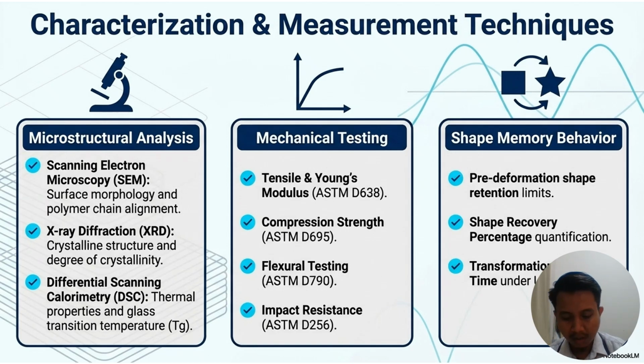For mechanical testing, all specimens will be prepared and tested according to the relevant ASTM standard. For tensile properties, for Young's modulus, for compressive strength, for flexural strength and impact resistance. For shape memory behavior assessment, samples will first be pre-deformed, either bent or twisted, to establish a temporary shape. UV will then be applied and we will quantify three metrics: the pre-deformation shape retention limit, the shape recovery percentage, and the transformation recovery time under UV excitation. These three metrics collectively define the shape memory performance envelope of each material under each UV emission.